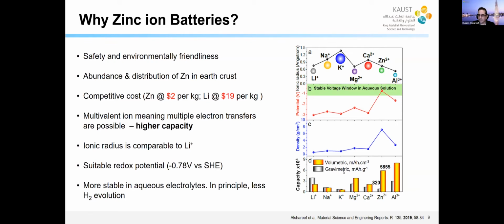And the gravimetric capacity is lower, but still high. This is because the zinc is dense, it has higher density than the other mobile ions. So it ends up with a smaller gravimetric energy density, but it's still very respectable. The ionic radius, if you look at the top graph, it's comparable to lithium. Although we should qualify the statement, in the end, it's not only the ionic radius, it's really the hydrated ion that matters, but nonetheless, it doesn't have too big of a radius to start with.